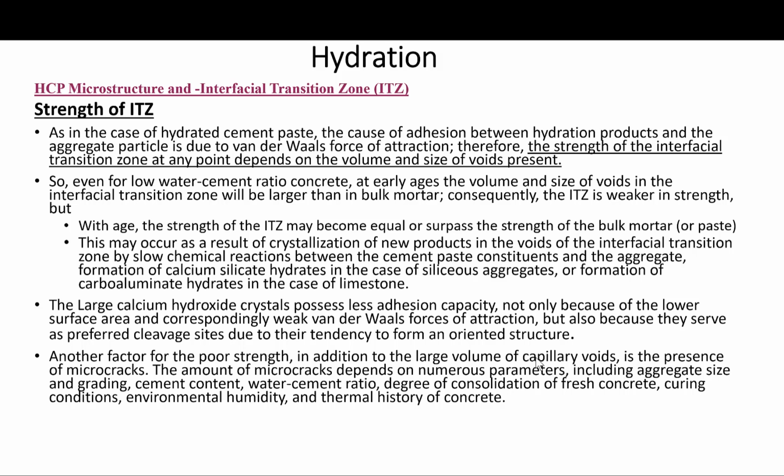Such differential movements commonly arise either on drying or cooling of the concrete. So in other words, a concrete can have microcracks in the interfacial zone even before a structure is loaded. So obviously, short-term impact loads, drying shrinkage, and sustained loads at high stress levels will have the effect of increasing the size and number of microcracks. So that's one thing you need to remember.